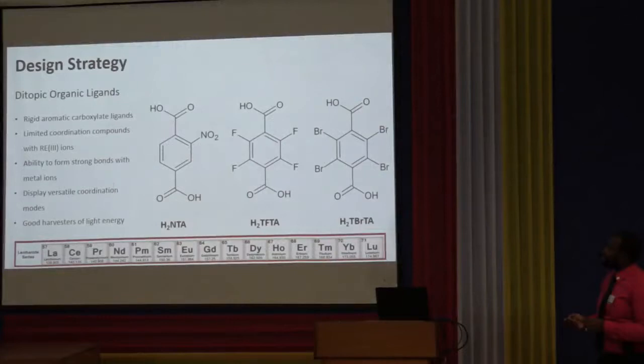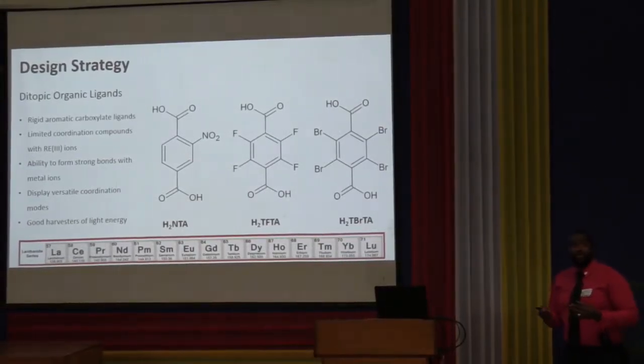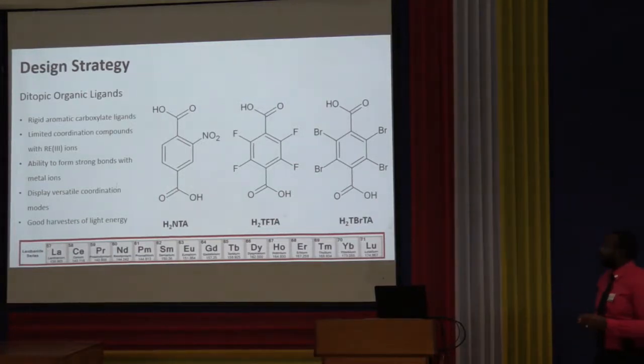When we analyzed the Cambridge Structural Database, we found that these ligands either had limited or no structures with rare earth elements. Also, the carboxylates bind very strongly to the lanthanide or rare earth elements, hence you have a tendency to form stable frameworks. Also, systems with conjugated pi systems are good harvesters of light energy, which can then be transferred to the metal centers, so we can exploit their photophysical properties.